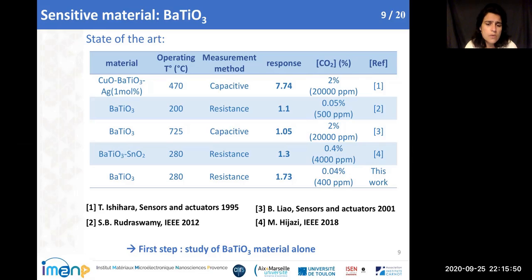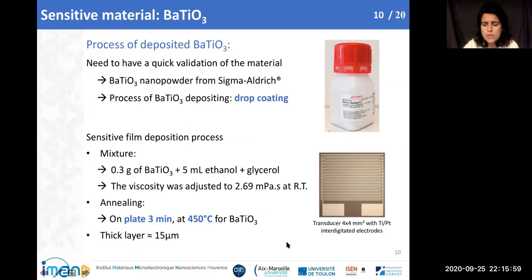The first step of this study was to fabricate a solution with barium titanate, with this material alone. So we bought nano powders from Sigma Aldrich. We mixed it with ethanol and glycerol, and we dropped it on a transducer. You have here the picture of our transducer with the platinum interdigitated electrodes. We adjust the viscosity of our mixture, and we anneal it during 3 minutes at 450 degrees, and then we measure the thickness of the thin film obtained at the end, and it was a thick layer around 15 micrometers.